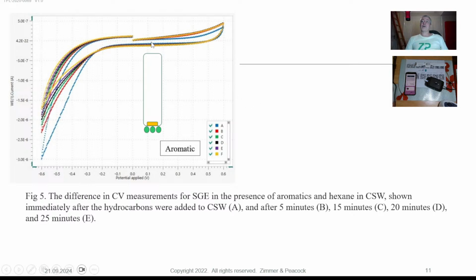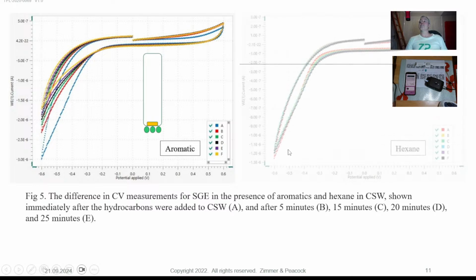So how do I understand this voltammetry? First of all, on a fresh electrode, you get the oxygen reduction. With time, the oxygen reduction decreases. Why does the oxygen reduction decrease? Because I think the aromatic compound is sticking to your surface and starting to block it, at least starting to block it to oxygen reduction.